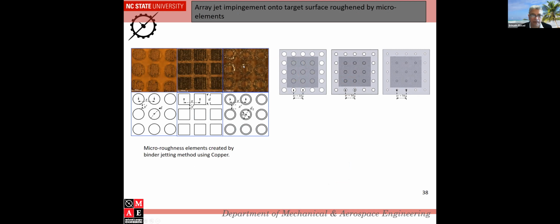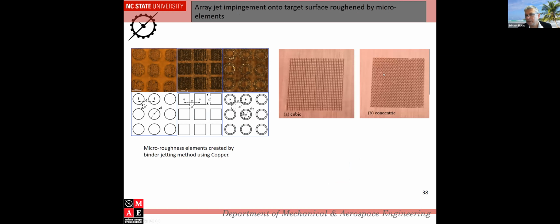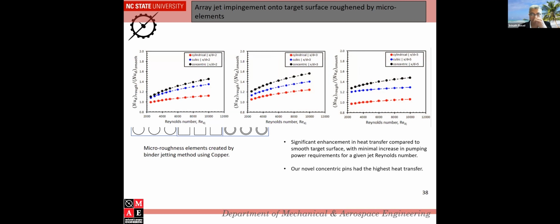This is a square pin fin, and this is a concentric pin fin. These were actually made with copper at Virginia Tech with my additive manufacturing colleague there. We found out that we can make such detail, and we have some flaws. You can see some flaws here, but in all, we got pretty good cubic fins. In the concentric pin fins, we didn't get it perfect, but we still got much higher heat transfer with concentric pin fins.